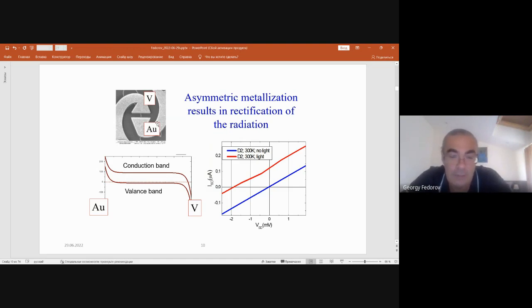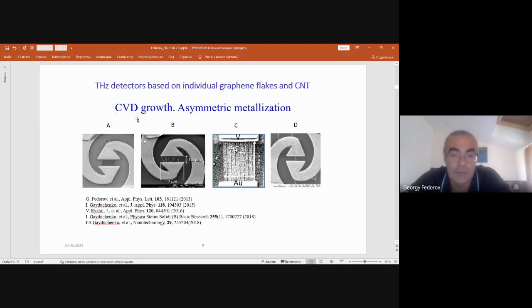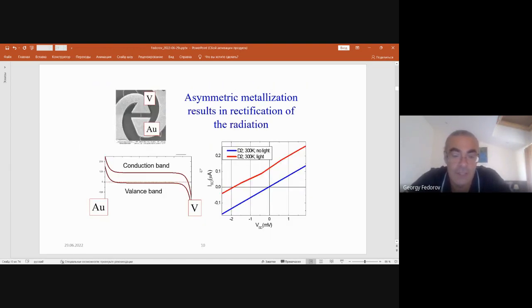So the idea which we employed in these four structures is the same. We have asymmetric metallization, which is done in a single sputtering step. So you have a thin vanadium stripe, in this case, touching your sample, your conduction channel, and you have a thin gold stripe touching your conduction channel on the other side.